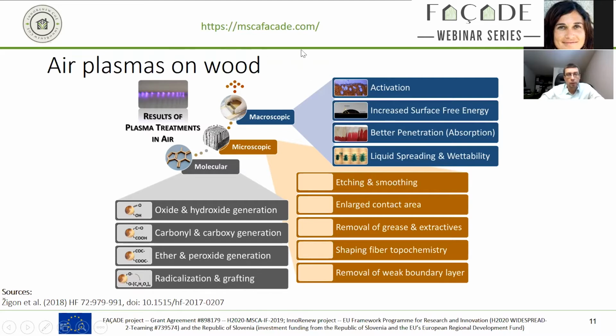Again, speaking about wood and other bio-based materials, the main components for many of these are lignin, cellulose, hemicellulose and holocellulose. Generally speaking, you'll find oxidation in all of these materials, much less so on the cellulose than particularly on the lignin. The lignin reacts most quickly, particularly with all the benzene groups included, so these are the most reactive to the species coming in from the plasma. This is also something to keep in mind: how this affects different parts of the composition of your workpiece.